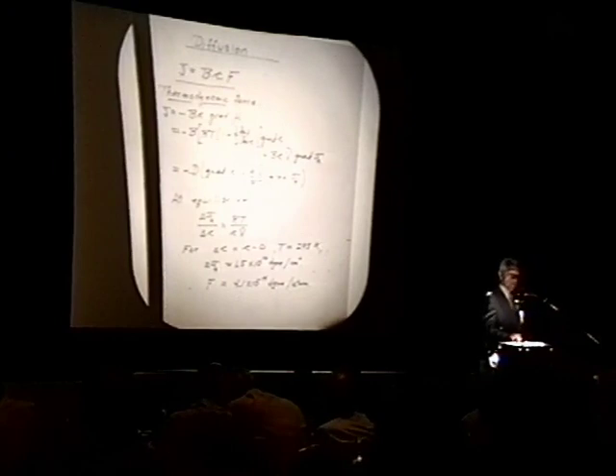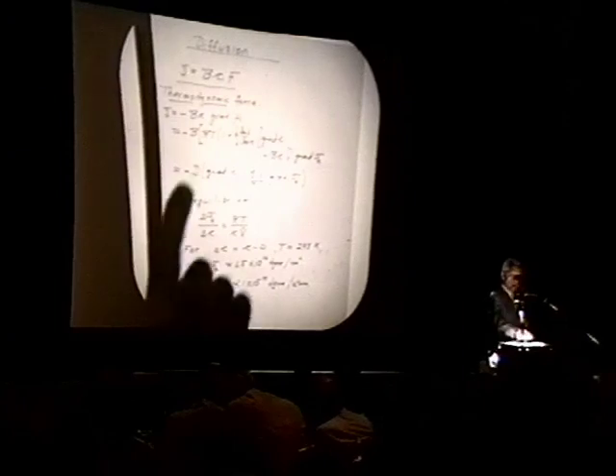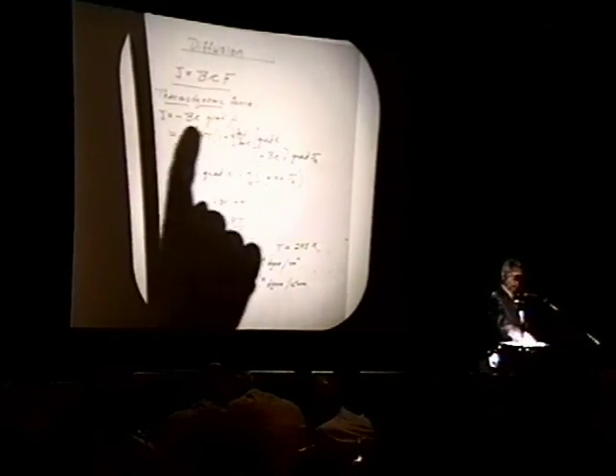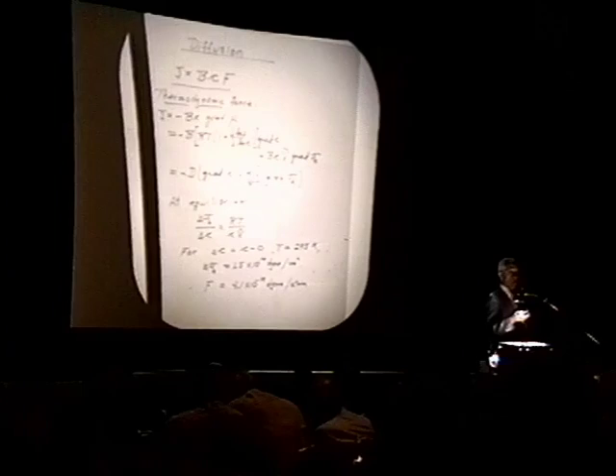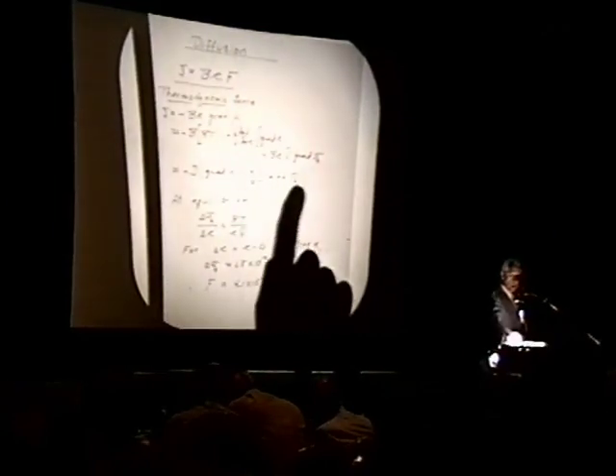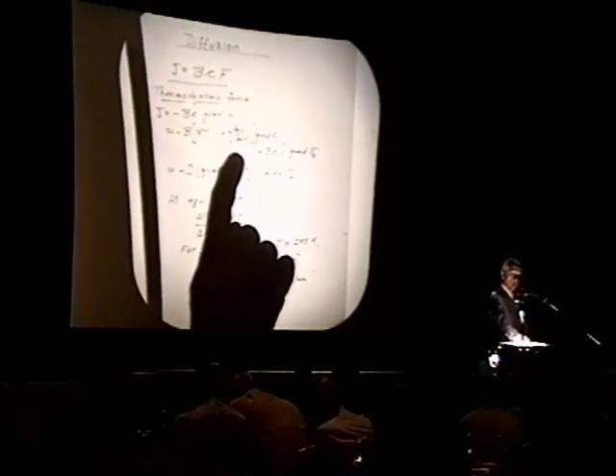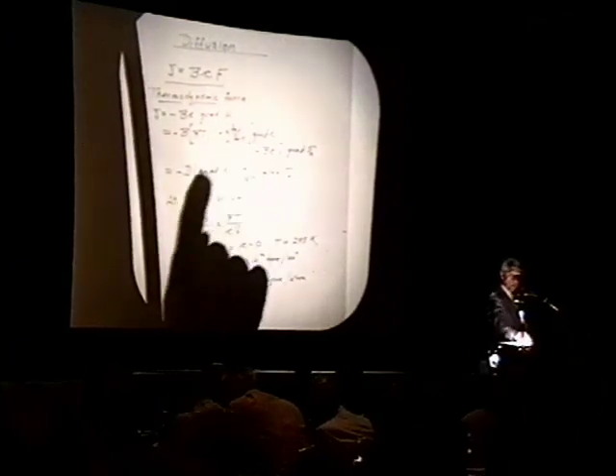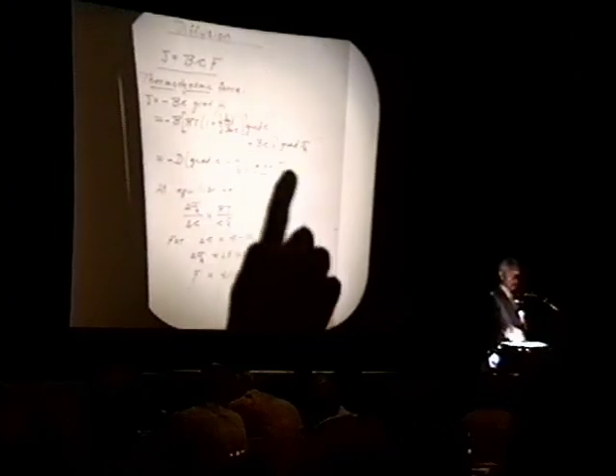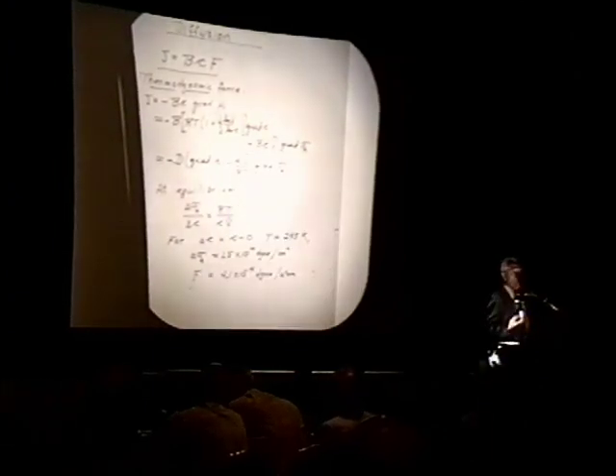In general, we have a diffusive flux J, which is motivated by the gradient of chemical potential. B is the mobility, C is the concentration. We can expand this to bring in the two important terms that contribute to the free energy, namely the concentration gradient times a thermodynamic term, which is the variation of the logarithm of the activity coefficient with the concentration. This can be very, very important. Here we have a contribution from the stress state, written in simplified form, forgetting about everything except the hydrostatic component of stress.